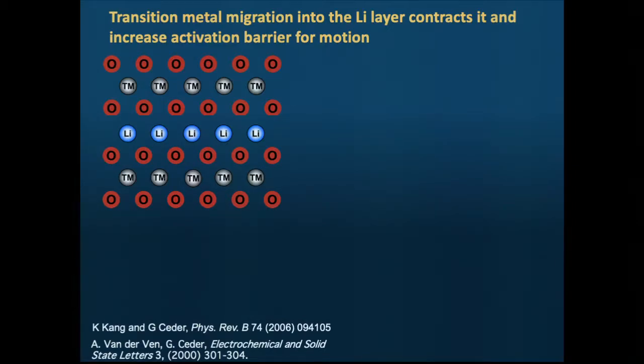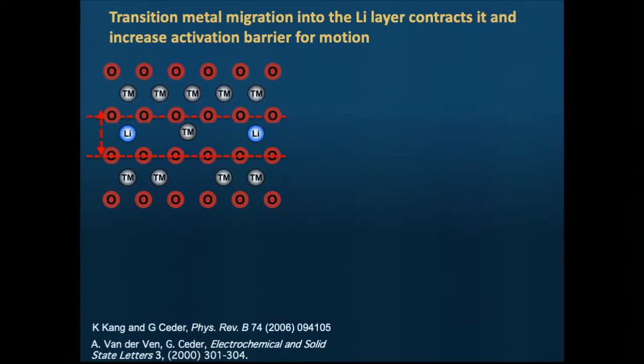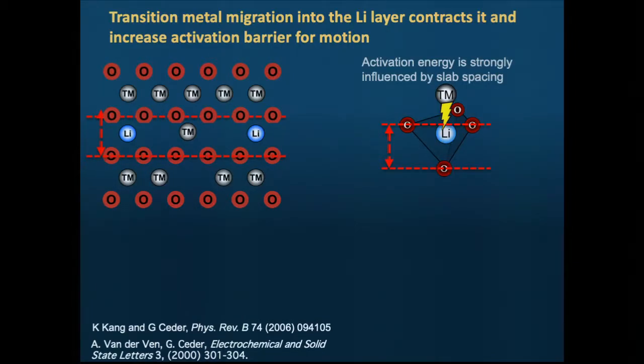If you take a layered cathode, and I made a cartoon here, when you charge the battery, you extract lithium, right? And in many materials you get an enormous amount of vacancies. We pull out as much as 75% of the lithium. So you create all these vacancies, and in many cases these transition metals will migrate in there because they have to make a single atomic hop to get in. And why is that bad? Because the transition metal has higher charge than lithium, 3+ or 4+, it pulls the oxygen layers closer. So it essentially densifies the structure. And what that does is increase the activation energy for lithium motion.